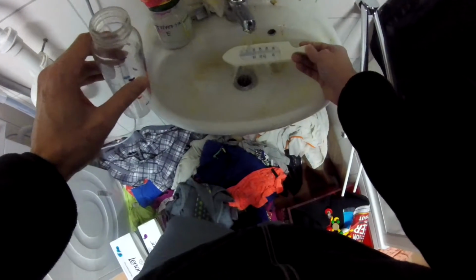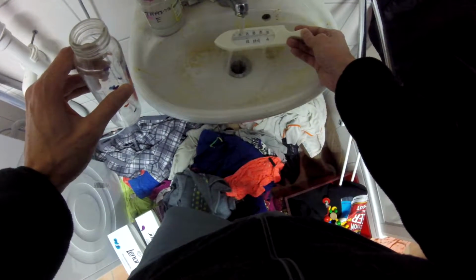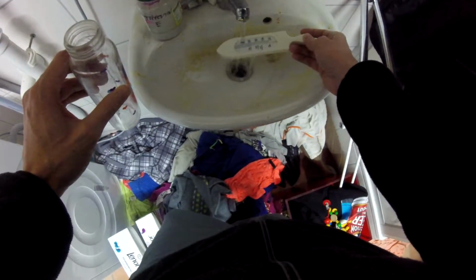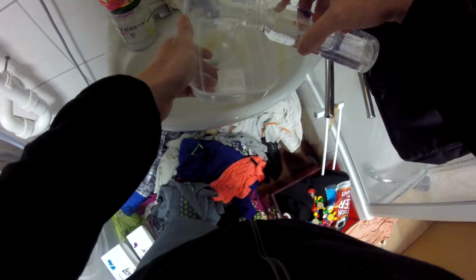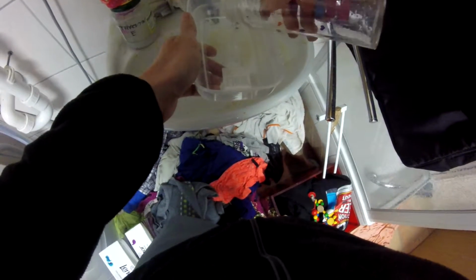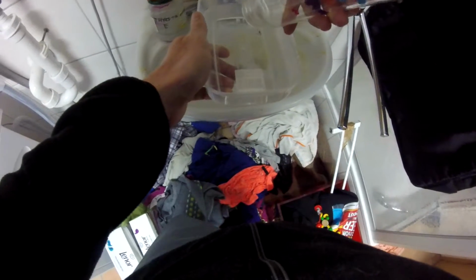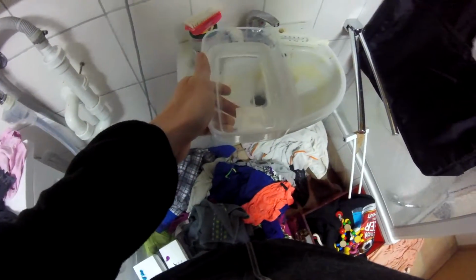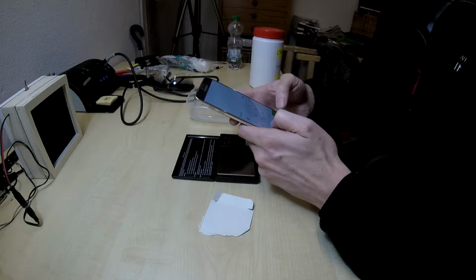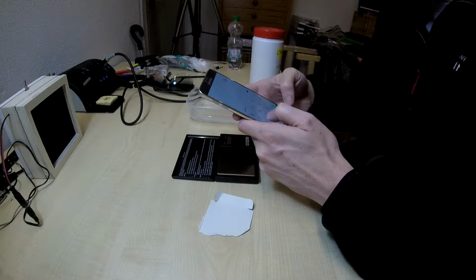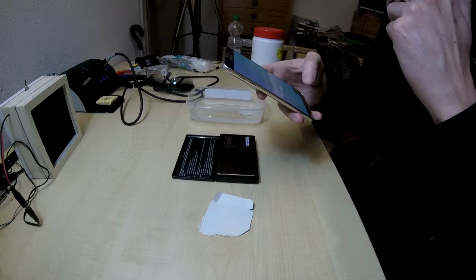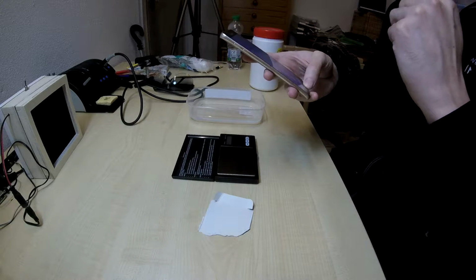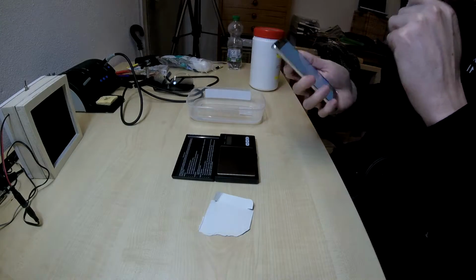Okay, now we need some warm water, about 20 degrees Celsius. Okay, this looks good. It's about 23 degrees, I think. 24. So we need 3.75 grams of sodium hydroxide for 250 milliliters.